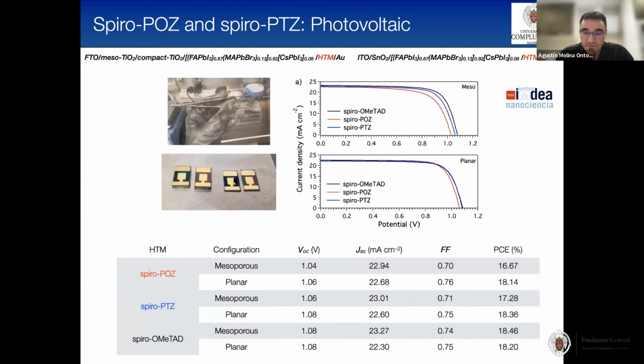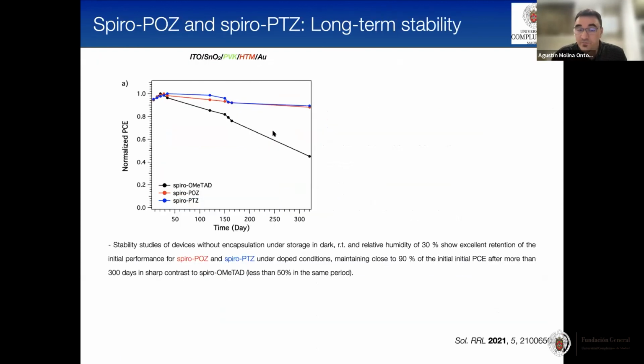So with these devices, if your perovskite is degrading, you can see the color change to something yellow. You go from something brown to something yellow. And in our case, it didn't degrade much because it was stable for almost 300 days. That was something good coming from the COVID, because we measured. This is the last day we measured, and then on the first day that we went back to the lab, we measured again, and our devices were quite stable.